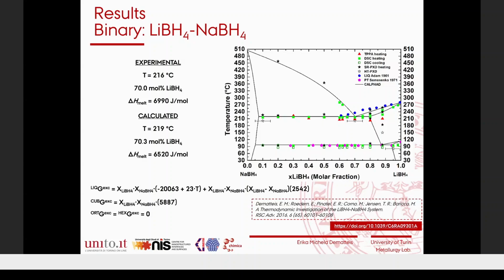With the CALPHAD approach, we were able to collect new experimental data using DSC or in situ synchrotron radiation X-ray diffraction, understanding the phase stability from an experimental point of view. After all, we collected this data and assessed using a parametric description of the Gibbs free energy of the liquid phase, of the cubic, orthorhombic, and hexagonal phase, which are related to this phase diagram.